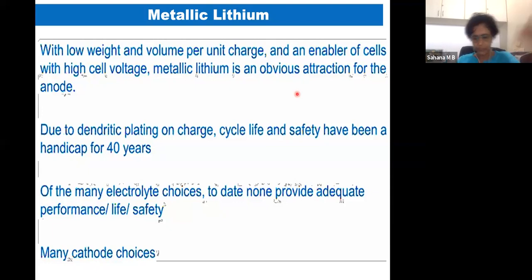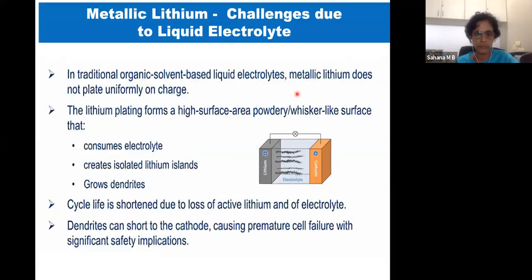Whereas with lithium metal, there is a possibility of dendrite growth, which can give rise to a short circuit. This kind of problem can be overcome by use of the solid state electrolyte. Solid state electrolyte does not allow the lithium metal to grow from the anode to the cathode. Therefore, instead of lithium ion batteries, we can directly go for lithium metal batteries.